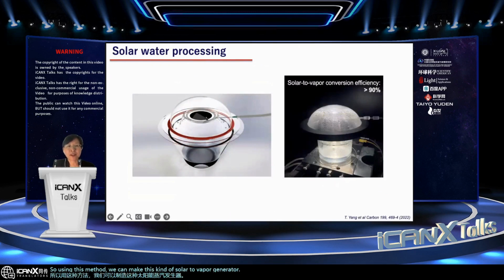So this is the graphene film, and we have seawater injected from the needle, and then by putting that under the sun, you will see lots of vapor generation, and the entire conversion efficiency can be very high, more than 90%.